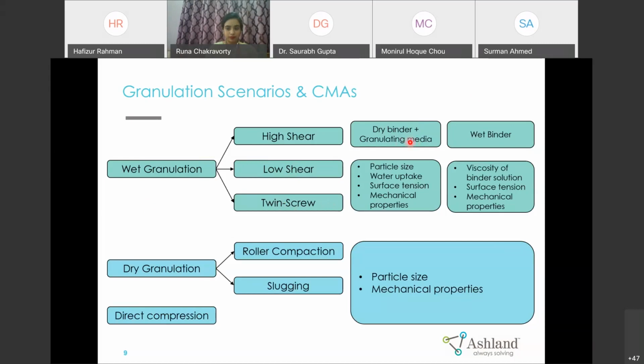And then here are the critical material attributes, where we are using a dry binder and doing granulation with water or organic solvent, and for a wet binder, where we are dissolving the binder in the solvent and doing granulation. So coming to wet binder, viscosity of the binder solution and surface tension of the binder solution are very critical. And when we are using a dry binder, then particle size of the binder is very important. Then water uptake, its surface tension and mechanical properties.